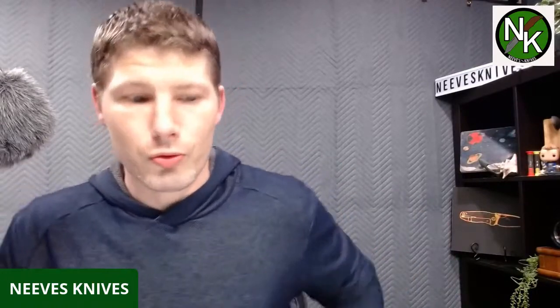All I'm going to say is that it pretty much did about the same, right around 14C28N, which obviously 20CV should do way, way better than. But that's a lot of what I'm talking about when I talk about some of these companies heat treating the M390, 204P, 20CV. Even if they have the recipe to get a lot of blades in a heat treat to all do well, a steel like M390, 204P, 20CV has a small margin where if they're over or under in the temperature and everything, it won't be as successful.